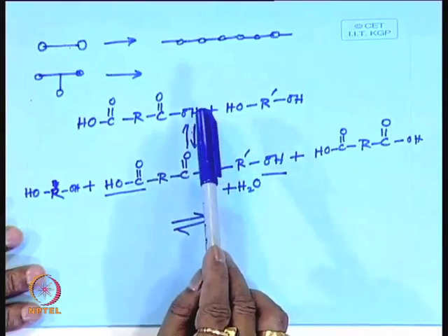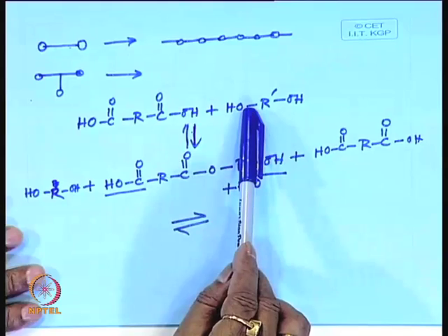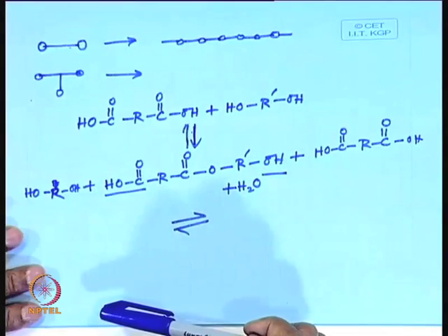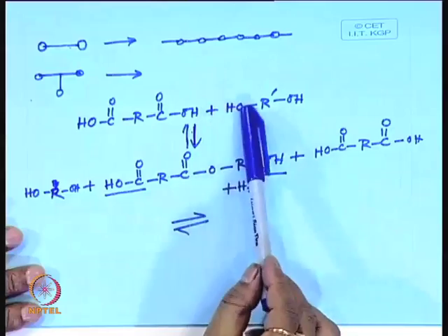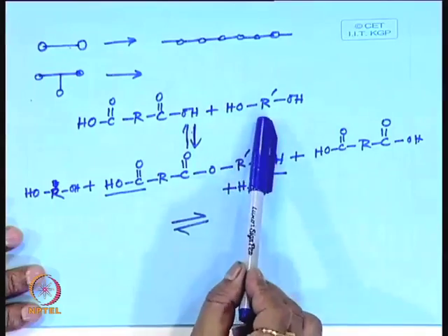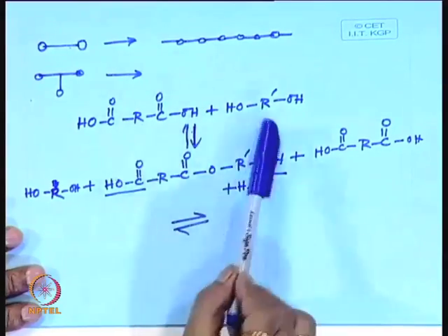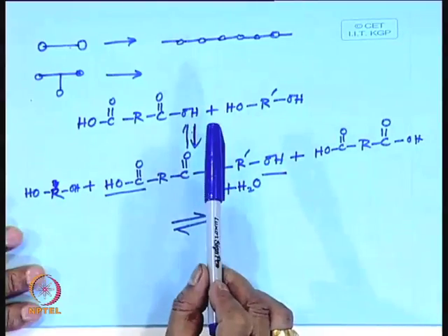This is a problem in condensation polymerization. What will happen? You will see later. You will see if there is some impurity or if there is some mistake during weighing of these two reactants, then you may not get a polymer of high molecular weight. Those who will be doing the lab class for synthesis of phenol and formaldehyde or synthesis of other polymers, you will see you may or may not get a polymer. If you do not get polymer, then you have to inquire whether there is something wrong in weighing or some impurities are there. So, you have to be very much careful.